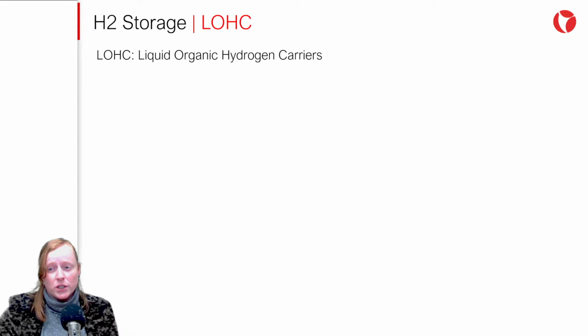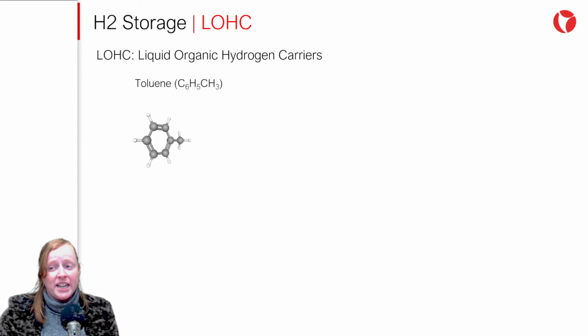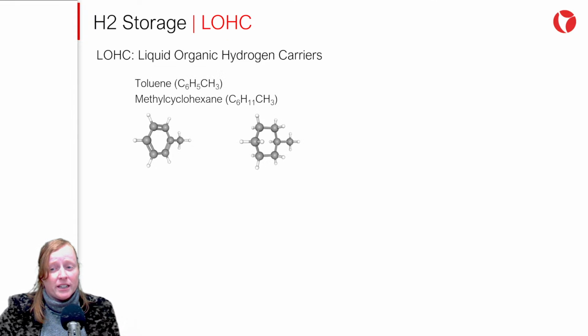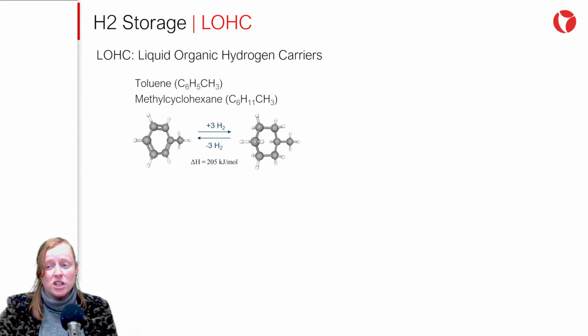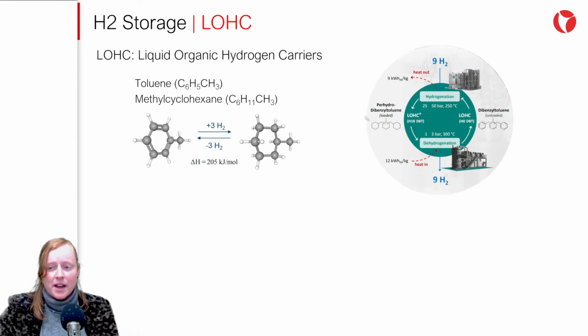Organic liquid carriers are an option for storage, but even more so for the transportation of hydrogen. Their use is based on hydrogenating an unsaturated organic substance, that is, one that has double carbon bonds, by saturating it with hydrogen. This example shows toluene, C6H5CH3, which has 3 double bonds. When hydrogenated, it becomes methyl cyclohexane, a compound that has 6 additional hydrogen atoms in its molecule. There are other organic compounds that can be used in this cycle of hydrogenating for storage and transport and dehydrogenating for hydrogen use. This graph shows dibenzyltoluene, which, when hydrogenated with 9 hydrogen molecules, results in perhydro-dibenzyltoluene.